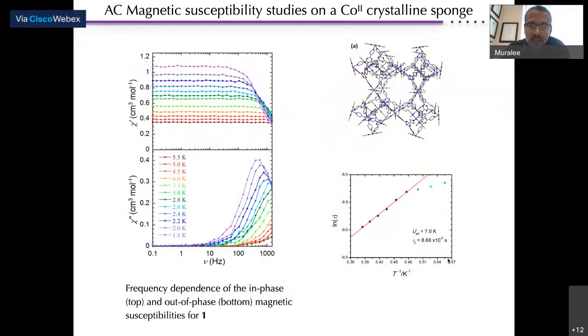One interesting feature is if you probe the dynamic susceptibility measurement, which is if you want to probe if your system acts as a magnet, you do dynamic studies, which is AC susceptibility studies, where you make the alternating current as a medium to probe the relaxation dynamics. In a way that if your system has a magnet-like behavior, there will be a blocking of the temperature, which we call the blocking temperature. And below that blocking temperature, the material will retain its magnetic memory, i.e., you will have the relaxation mechanism in the AC data as shown here.